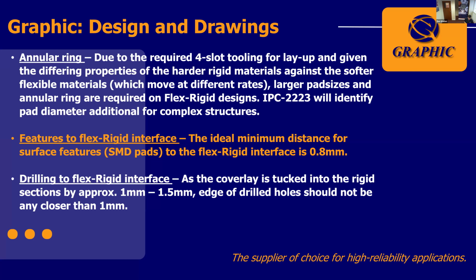So what we typically say here at Graphic is the ideal distance for any SMD pads to that flex rigid interface is around about 800 microns, 0.8 millimeters. When it comes to the drilling, we typically say that the drilling should be around about 1 millimeter from the edge of the drilled hole to that flex rigid interface. Because the coverlay, and I'll show you some examples in a minute, is tucked into the rigid section by around about 1 millimeter to 1.5 millimeters, this is another reason why we don't want to have holes too close to the rigid interface, because the last thing we want is to drill through adhesive that then might affect the in-hole plating and the hole quality.